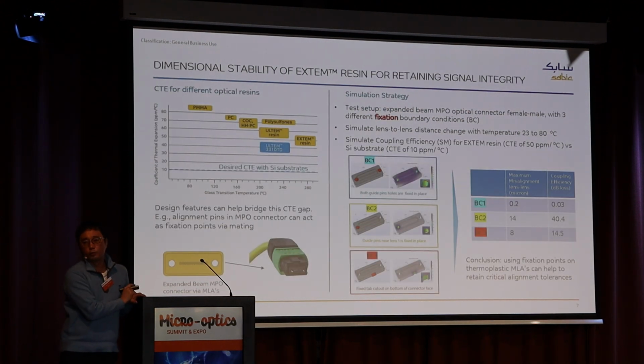Up until now, we talked about all the good things of our materials, but we are honest, there are also some shortcomings. So here we showed the coefficient of thermal expansion, or CTE. Our materials, EXTEM and ULTEM, actually have lower CTE than other competitive grades. Also, we have this low CTE EXTEM resin, which has around 35 to 40 ppm per degree. So it's extremely low for a thermoplastic, but in the photonic integrated package, these lenses should be aligned with a PIC that is silicon or glass. Then there's a huge difference in CTE. So there, of course, glass lenses have an intrinsic advantage in this respect. Most probably, thermoplastic cannot match the CTE of glass.